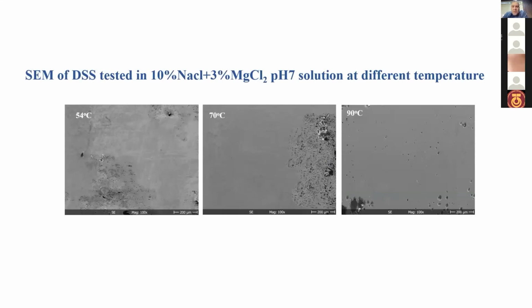Also, the optical or scanning electron microscope shows that there are a few pits and very small pitting on the surface of the sample tested at 54 degrees centigrade. This gradually increased in size and number of pits with increasing temperature and became large at 90 degrees centigrade, as we show here in the third picture.